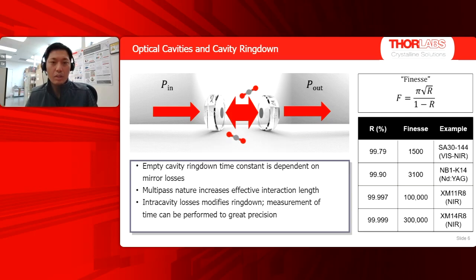So if you couple some light into a Fabry-Perot cavity, that light will bounce around in the intracavity space, and each time it hits an end mirror, a little bit will leak out. Now, that leak rate is going to depend on the losses of the mirrors. So the lower the losses of those mirrors, the longer the light is trapped inside, and the decay of that light outside the cavity is going to have a longer time constant. And so that drives the motivation for very low loss mirrors. And then once you introduce an analyte or an absorbing species into the space between the mirrors, you'll introduce a little extra loss.